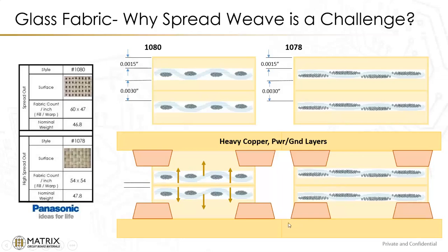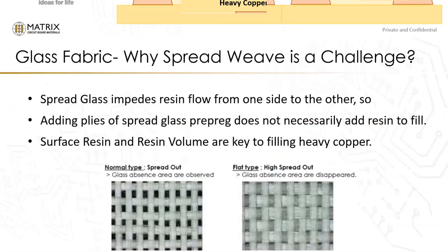So there's two things with that. So one is possibly having glass stop because of the heavy copper feature, depending on what it is and how much you're trying to fill. Because this glass is getting pushed to those copper features, you may end up with a situation where there's not much resin between the actual glass and the copper feature because of the low pressure area, both top and the bottom with that, where you get a little bit more space because of the open weave with it.